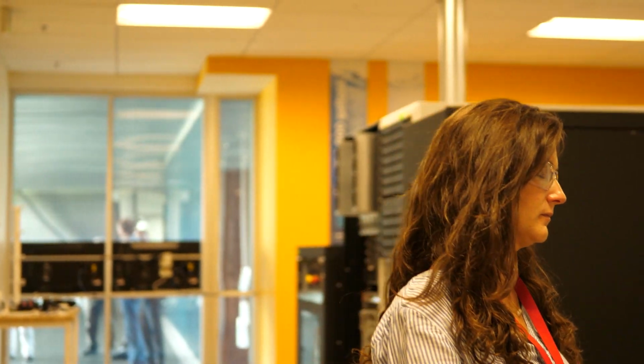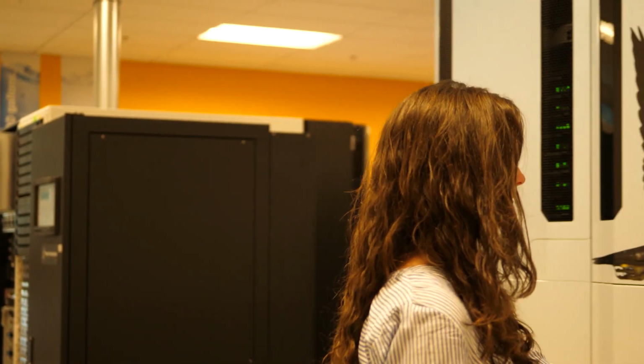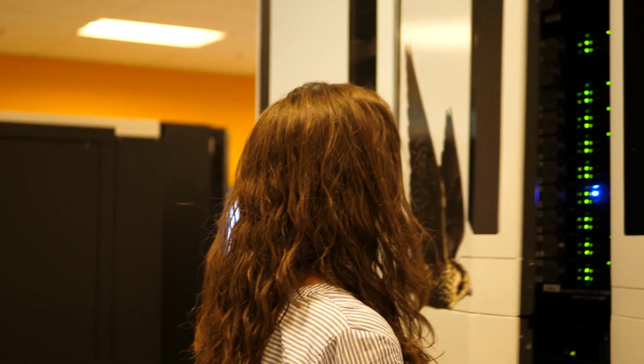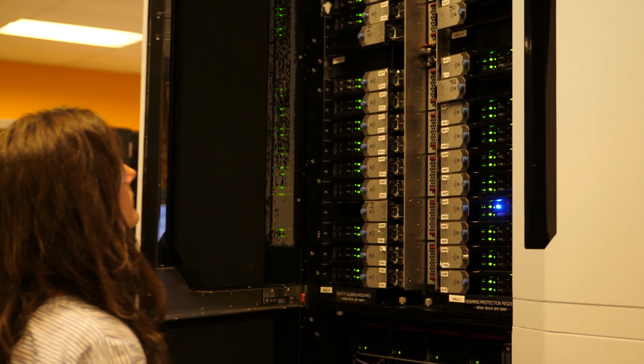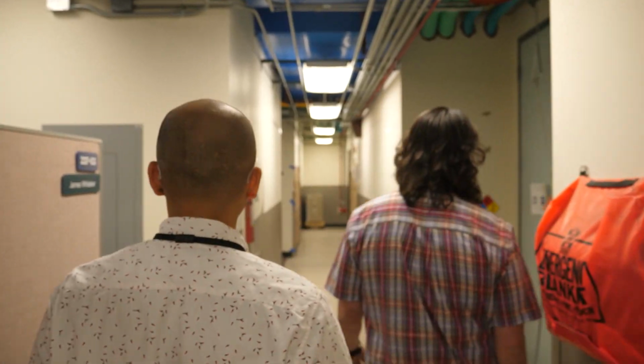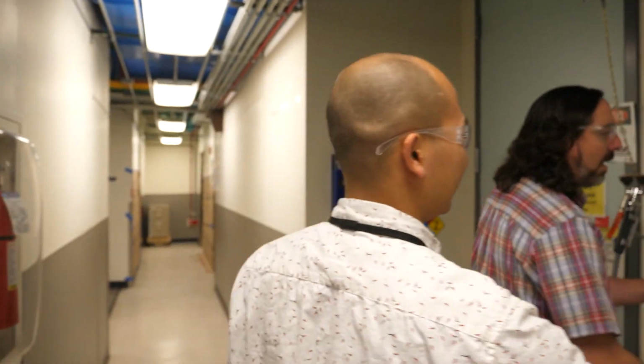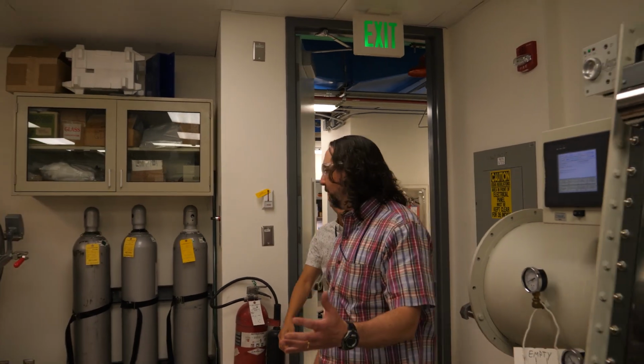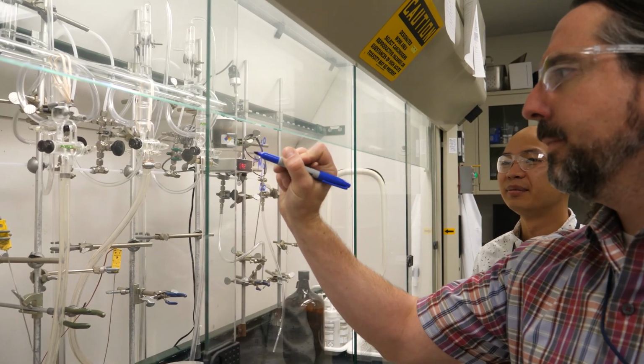petaflops. We use atomic scale modeling combined with experimental kinetics and catalyst characterization to understand how reactions occur on catalyst surfaces. We use that information to understand what's limiting the catalyst activity or selectivity, and then propose modifications to the catalyst formulation to try and improve performance. Once we've identified computationally interesting candidates, we need to make these a reality using innovative synthetic routes that we've developed